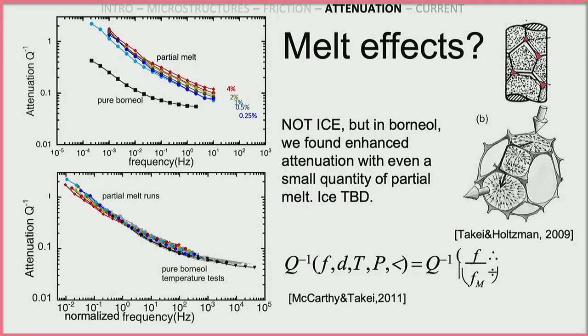But I did study this, as Mark alluded to, when I was in Japan. And so this is, again, this organic material. But again, my intuition about how materials with similar dihedral angles should behave, I think we'll probably get a similar response. And that is that as you increase melt, you get an increase in attenuation. And why is that? Well, that same mechanism of relieving the stress at concentrations by diffusion around the grain boundaries: if they don't have to take this long path, if they can take a superhighway through the melt, it makes the whole process a little faster. So the idea is that with increased melt, this grain boundary process is sped up. But it also affects both modulus and viscosity in the same way, so when you do that same normalization, it collapses to that master curve again, which is nice.